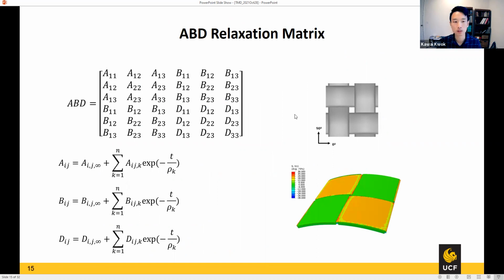But what we really want is not to carry all these three-dimensional constitutive equations all the time, because that's going to be very heavy computationally. So what we do is a dimensional reduction, just like plate theory, and in the end arrive at a constitutive equation in terms of moments and in-plane forces, and that gives us less. You can describe that with just the ABD matrix again. This is now not elastic but viscoelastic, so all of these terms are Prony series. You can get that purely from the computational simulation.